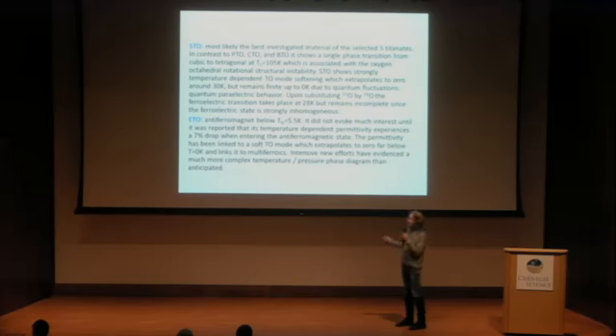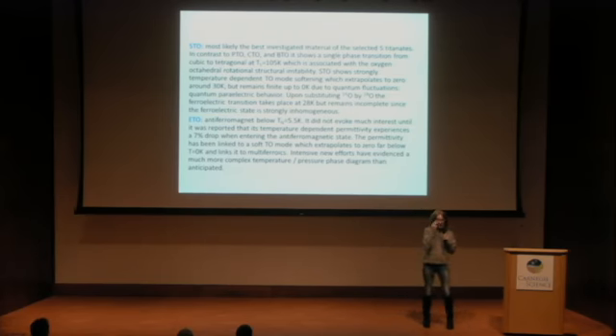Europium titanate is antiferromagnetic below 5.5 Kelvin. This has been known for almost 60 years. And it was supposed to be very boring until the group of Stanislav Kamba and the Czech group found a dielectric anomaly with a drop of 7%, which can be related to a soft mode. And from then on, it was in intense research due to the fact that it could be a low-temperature multiferroic. But this is not the issue.